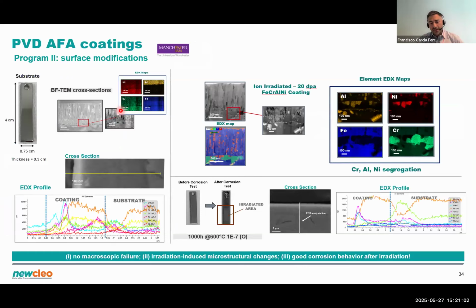And what you find with these kind of coatings is that the irradiation is inducing some segregations, but despite that, we still see a good behavior in the corrosion test that we performed under screening conditions, so 600 degrees, 10^-7 oxygen content, which was a positive surprise, say, in spite of these segregates that ion irradiation is inducing. So a promising route to explore in the context of a PhD thesis.